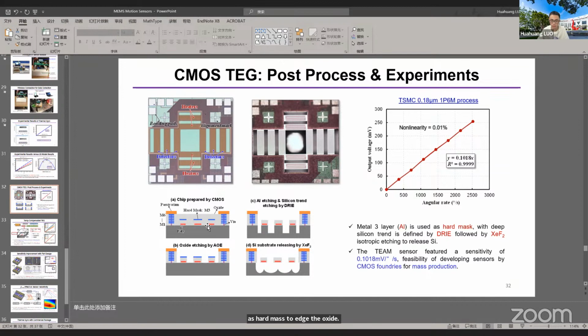You mean the thickness of this metal M3 is 0.5 micron? 0.5 micron for the metal 3 layer. No, actually, because I use CMOS foundries to fabricate this sensor, for each layer, the material is not realized by me, but by the foundries. I just did some post processing in NFF. But I'm not sure if they use sputtering or evaporation. I guess it should be sputtering.